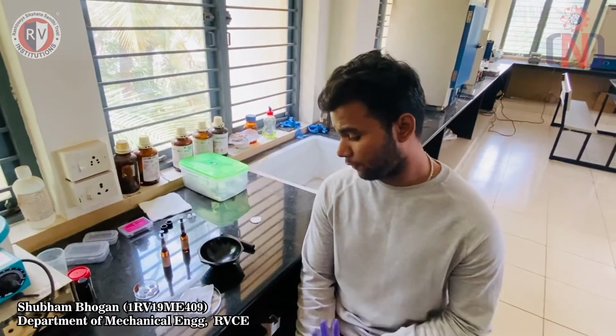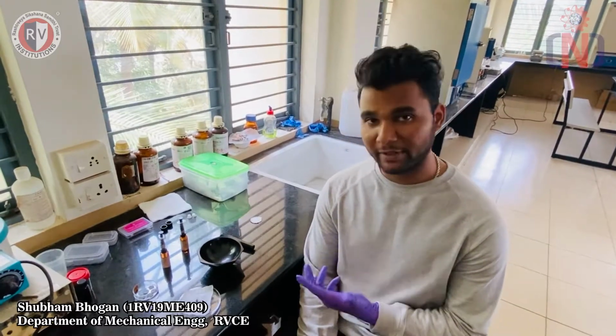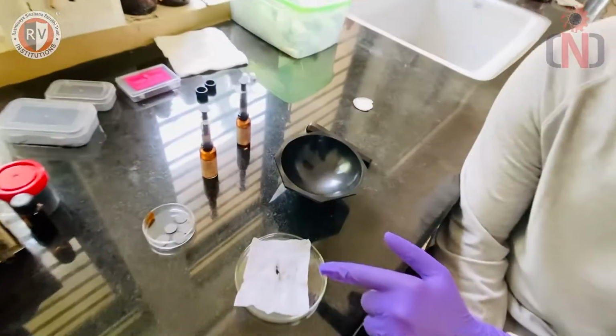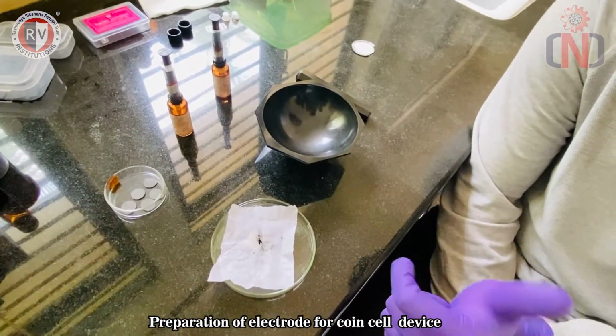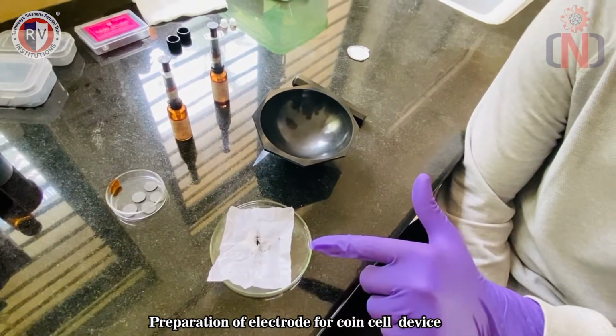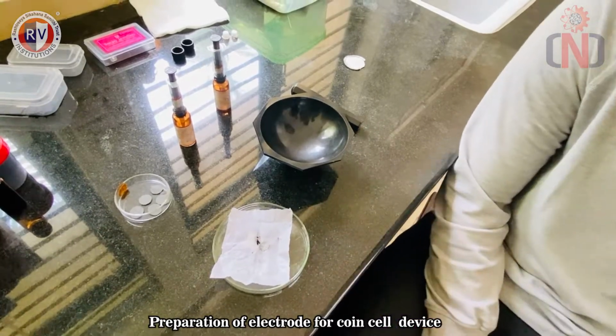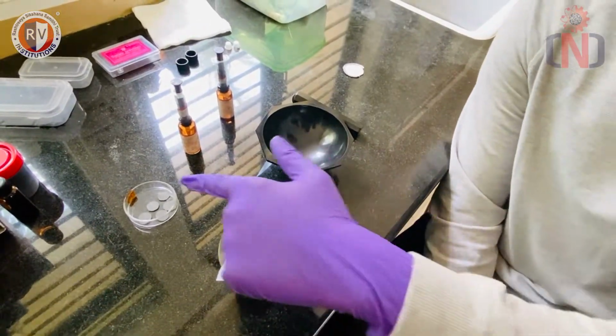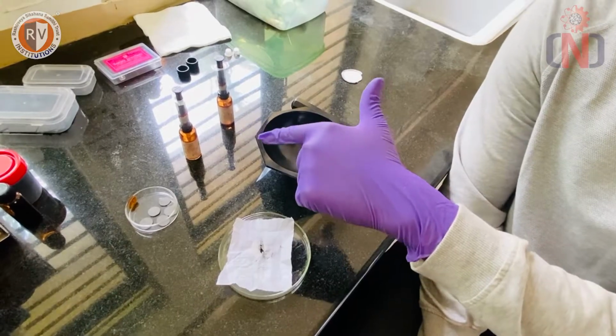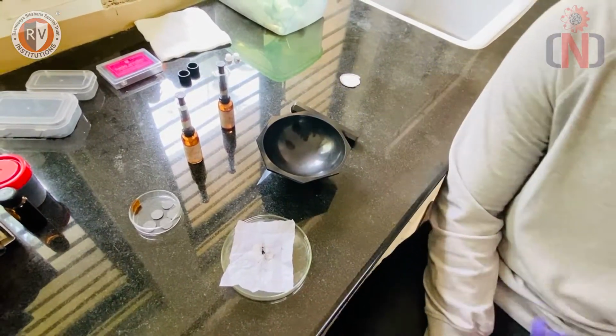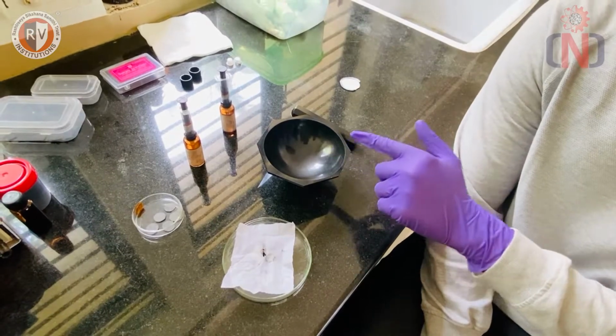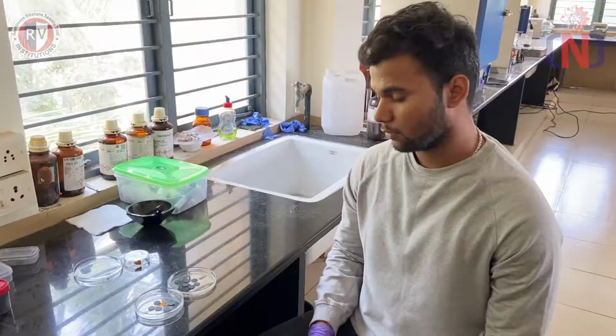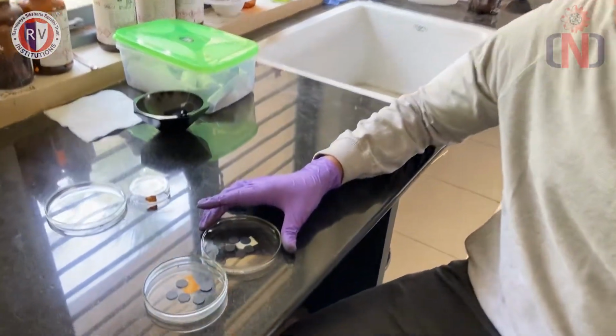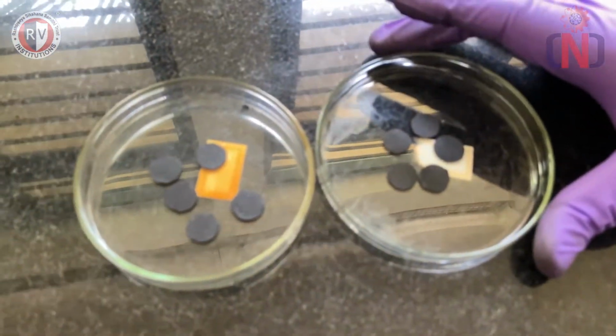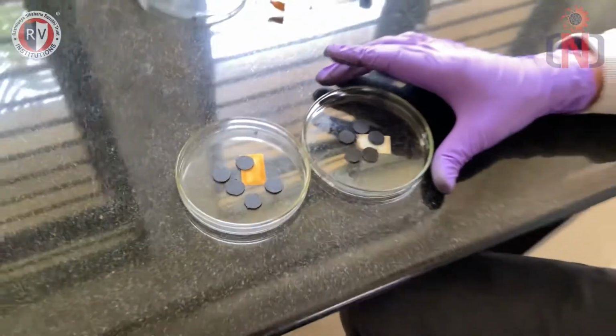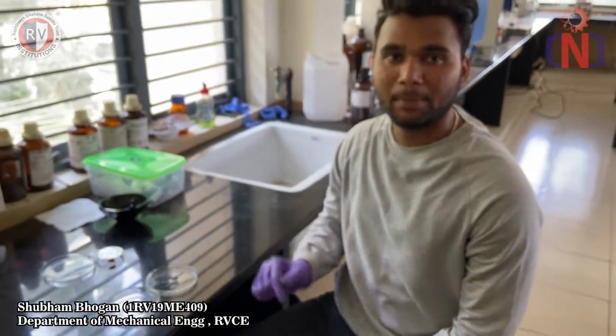After preparation of nanomaterials, we are going to further proceed with preparation of the electrode. This is our nanomaterial which we have synthesized in our laboratory, which is a very promising material for supercapacitor application. For preparation of the electrode, we need carbon sheet, PVDF which is a binder, and NMP which is a solvent. All together are mixed in a mortar and made into a slurry to paste on a working electrode. So these are the working electrodes which we have prepared by applying the slurry on a carbon sheet and then dried, which will then act as working electrodes for supercapacitor coin cells.